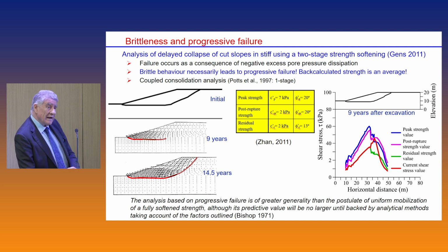And all this could actually be demonstrated using simple finite element analysis without any assumption, just putting in the brittle behavior of the material and allowing the pore pressures to recuperate according to the permeability of the material. Nothing else. And that was done by Potts. We did that in two stages, going from peak strength to post-rupture to residual strength. The results were similar, and we can see that certainly you get failure decades or many years after the excavation. It's a progressive failure. Here it has failed along this area, and then it will continue until a full sliding surface and a full loss of equilibrium occurs.